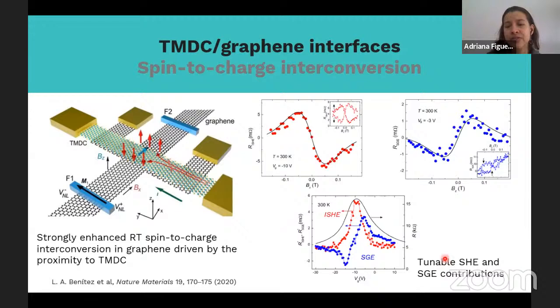So you find tunable spin Hall effect and spin galvanic effect on those interfaces, and this is all a way to demonstrate that you have spin-orbit coupling being imprinted in the graphene from the TMD. But all these measurements are indirect.